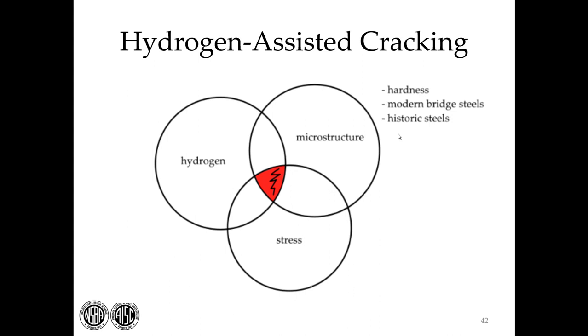And stress, in terms of stress, that's hard to avoid. In a typical girder, we don't get a lot of residual stress in the types of welds that we build, and nothing that's going to overcome the strength of the weld to cause cracks. But sometimes we do encounter that in highly constrained situations. But for the most part, the constraint that you have in a joint is based on how it is set up. So there's not a lot you can typically do about that.